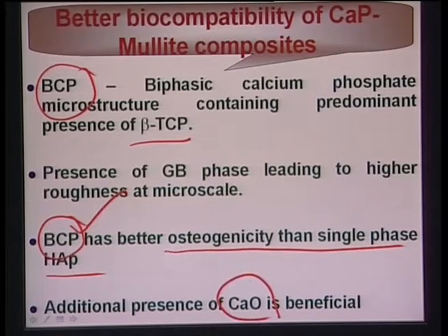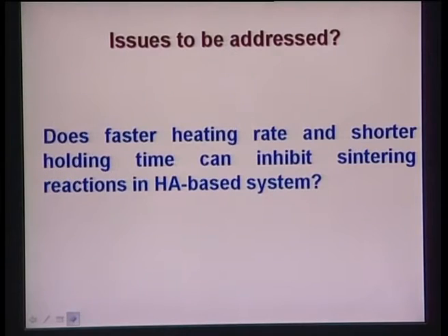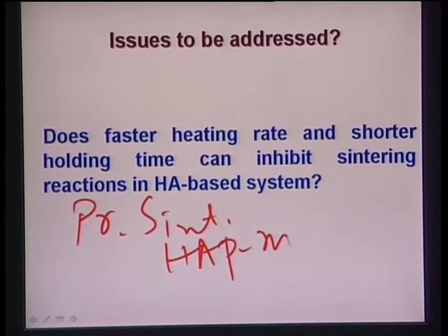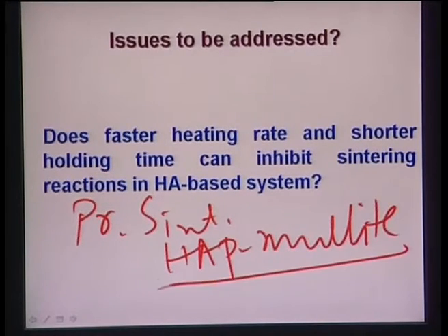Third, as you remember from the TEM image, the transmission electron microscopy image, these materials have calcium oxide, and the additional presence of calcium oxide also influences the biocompatibility property. Now, pressureless sintering of hydroxyapatite always leads to multiple phases, and these phases also influence the mechanical properties to some extent. Next, the results of the experiments that I'll show demonstrate how these sintering reactions can be avoided in this hydroxyapatite based system.